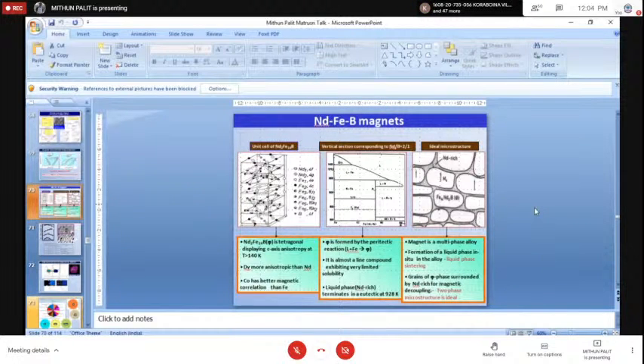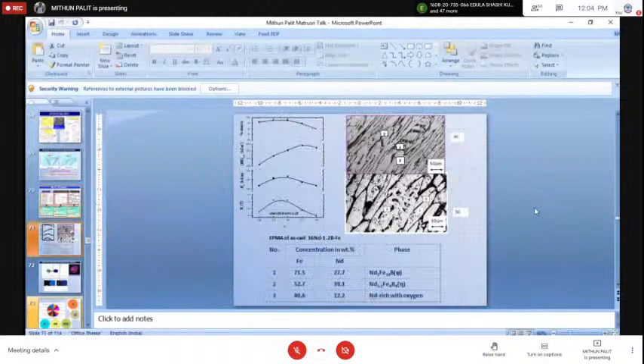Because if one of the particles loses its magnetism due to application of an external field in the opposite direction, and the channel of communication between two particles is very strong, then immediately it will influence its neighbor and demagnetize it. However, if the shielding is efficient, even if one of them is demagnetized, the effect will not immediately be realized in the neighboring particle, and thereby the material will have very strong coercivity. So this microstructural engineering is also very important, how to create such a nice envelope all around the 2-14-1 particle.